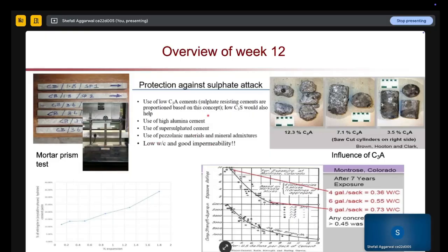Other thing, first is we are using low C3A cement. Next thing is we can use high alumina cement, then we can use super sulfated cement, and we can use some mineral admixture, low water to cement ratio, and good impermeability. If we go through all these things, we can protect our system against external sulfate attack. So here you can see different types of material: this is concrete having 12.3% C3A, this is 7.1 and 3.5% C3A. You can see this white crystal forming, right? In a low C3A cement, it is a very dense material with less ettringite formation as compared to higher C3A cement.